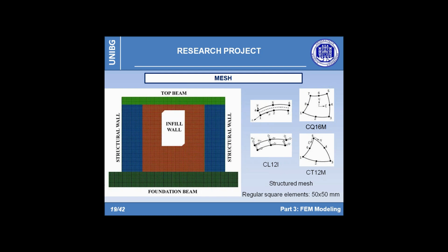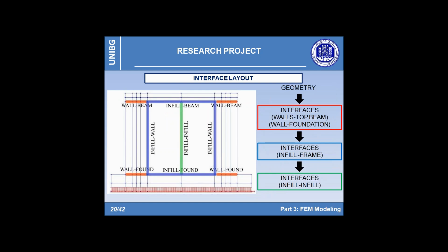Moreover, trying to reproduce the interaction between the parts making up the specimen, interface elements having zero thickness have been adopted. As shown in the figure, 3 different kinds of interaction have been modeled. All the interfaces are only elastic, and in particular, the ones highlighted in red simulate in a simplified way the sliding occurring between the shear walls and both the top beam and the rigid foundation.